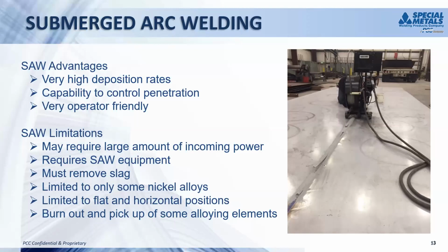The other thing to just be aware of, on that same note, you do tend to burn out some of the niobium and the chrome when you're doing submerged arc welding. So you need to be cautious that you're getting all the strengthening elements in a solid solution alloy that you think you're getting as well. Next slide.